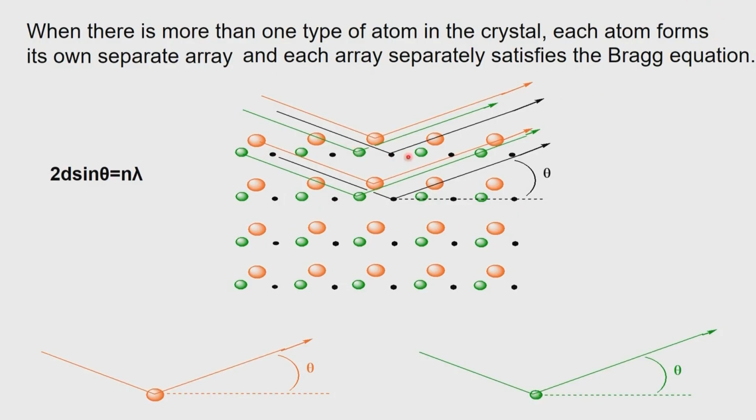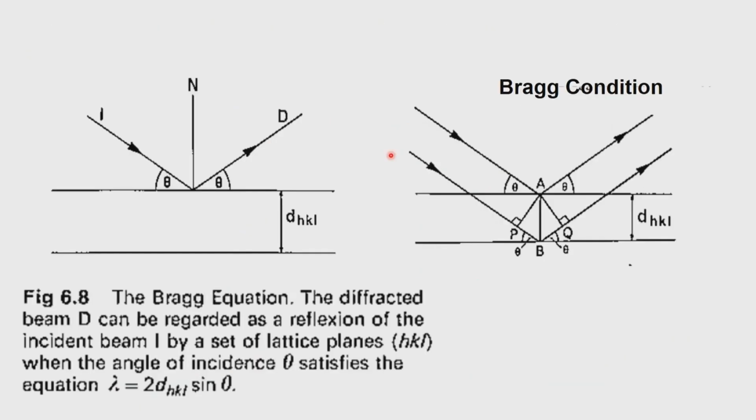But the fact that we are getting it from the various planes, which we can locate by Bragg's law or for that matter Laue's condition, tells us that it is in principle possible to find where these atoms are, depending upon the intensity now. So, until now we depended upon the directions to get the geometry. The intensity associated with the diffraction spot will tell us where the atoms are. If, for example, this red atom is associated with this lattice point, then the intensity will be totally dominated by the presence of that red atom. Okay, so that is the logic which we will follow in getting into the details of how the scattering occurs.